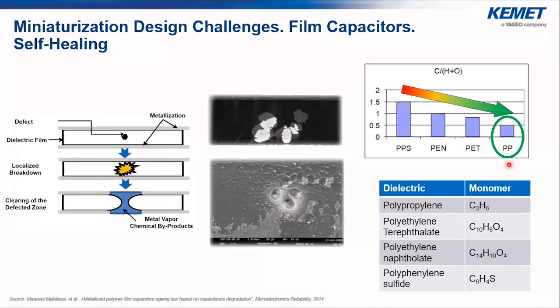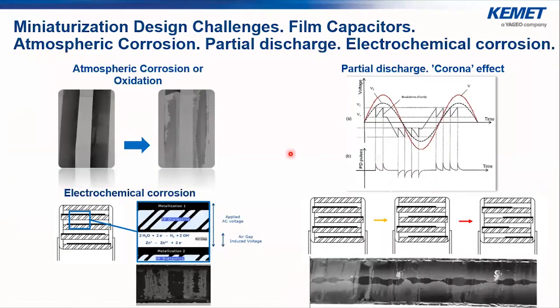As you can see here, polypropylene has the best self-healing properties due to its really good chemical composition, which is really visible here compared to the other listed polymers on the slide. On the other hand, the oxidation of metal electrodes is mainly caused by the chemical destruction of metals due to the presence of water, oxygen, and other corrosive media. On the slide are shown the conditions of two metallized films before and after the oxidation phenomenon. This process is active even without voltage, but its magnitude in encapsulated capacitors is more often negligible, as the reaction rate is limited by diffusion of oxygen into the part and is strongly limited by the compact film winding and thermosetting resin